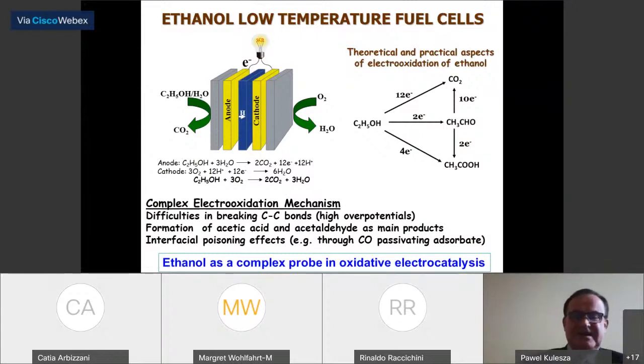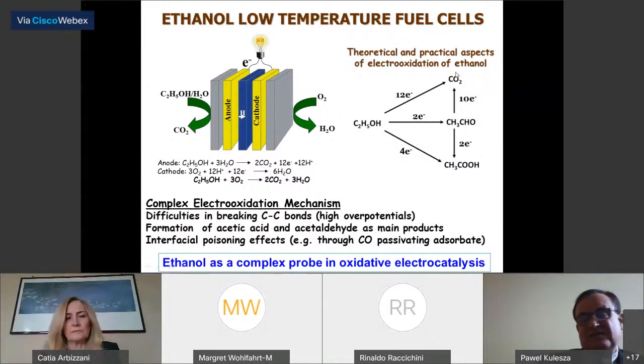Okay, we worked with methanol and ethanol with Roberto too. There was a period that people believed that ethanol is a fuel. They still believe, but there are some fundamental problems to be resolved. Ethanol is difficult to handle because you have to break the C-C bond. There is not such a problem in methanol. In methanol there is a problem, like in all small organic molecules, of poisoning with carbon monoxide. So to make the system effective, 12 electrons, you need, basically speaking, to search for very good catalysts.